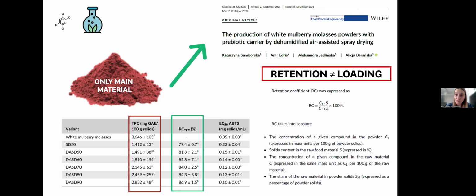This type of calculation, this retention coefficient, allows to exclude the carrier from the calculation. That is why we can directly compare the degradation of bioactive compounds in the powder and with the raw material prior to spray drying. That is why it is, in our opinion, so important to take it into consideration while expressing the retention coefficient, eliminating the carrier from the calculations.